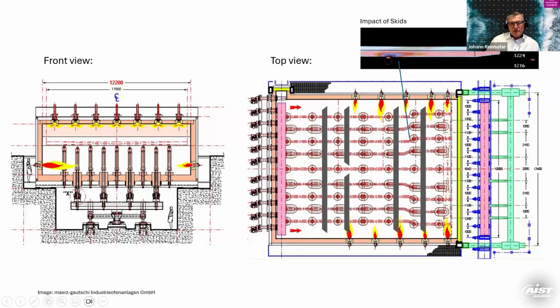We move through the furnace, and at a certain point here, we go offset with the carrier system, because we want to avoid cold spots on the lower end of the slab or the billet, because that will affect the rolling process. So we have a little offset here. So we give this spot here the option to heat up until the end of the heating process, and then we take the billet or the slab out with the discharge machine and go into the rolling mill from here.